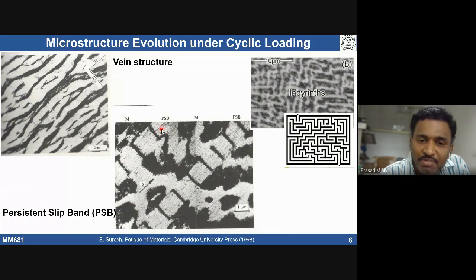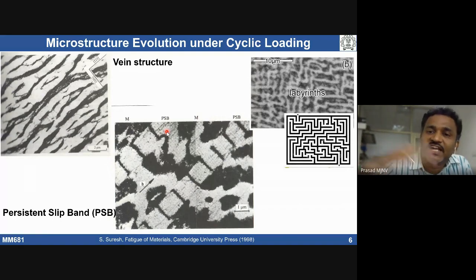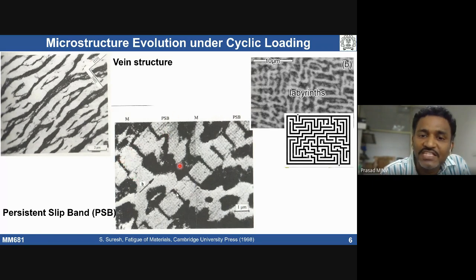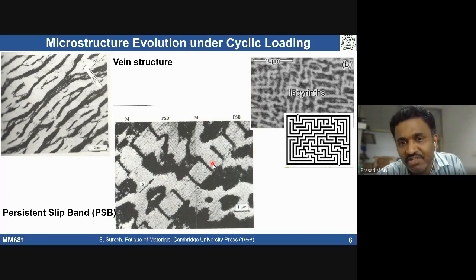The persistent slip band is nothing but a rearrangement of dislocations. When you deform the material in different directions, changing between the positive and opposite direction, annihilation of defects can take place very easily in certain locations. That can lead to formation of nice bands. Those bands are called persistent slip bands. The combination of persistent slip bands in some places and the cell structure may give you a labyrinth kind of structure.